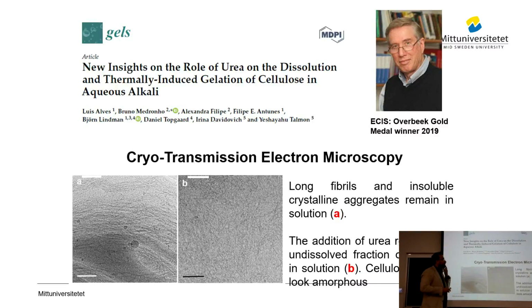Keeping track of new techniques to characterize cellulose, we ended up doing some work also with Ishi Talmon from Israel, who is a known guy in terms of electron microscopy. The problem is that in these cellulose solutions, you often have a lot of salt. They are highly concentrated, acidic or alkaline solutions. So to vitrify the species is always very tricky. And Ishi has the knowledge to solve that. And we were able to do that on the sodium hydroxide-based solvent.